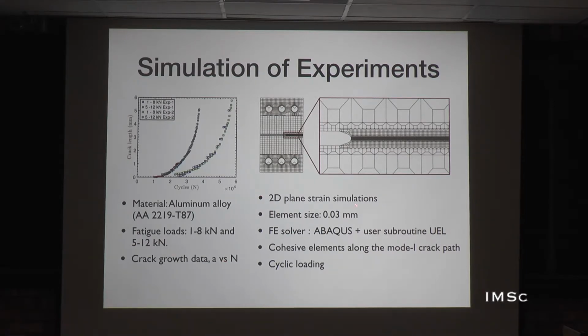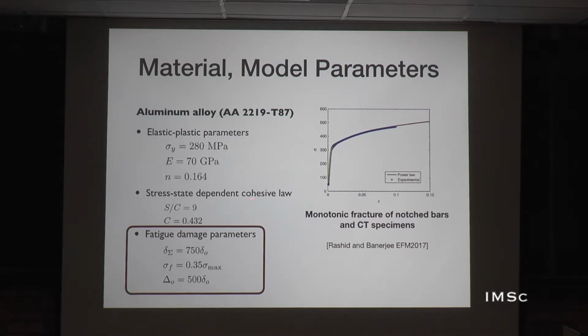For this we do two-dimensional plane strain simulations, and some details are here. We have put cohesive elements along this path, and we have applied cyclic loading, and the way I told you how the damage is accumulated, we do predictions of element failure. For the continuum properties, we had done monotonic fracture of the same material earlier and had found some of the stress state dependent model parameters. I am not stressing on these because that is not the focus. All I want you to take from here is that we found some set of parameters which were able to